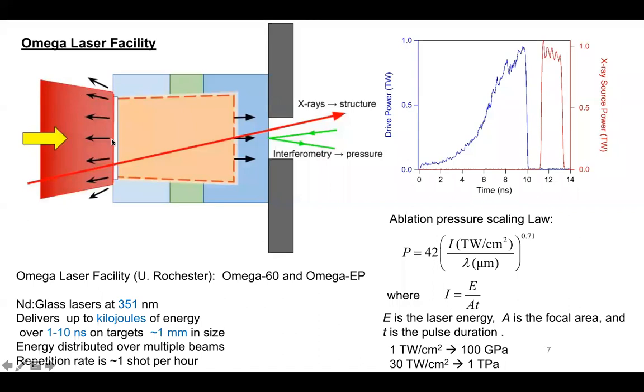We drive off a plasma at high velocity, heating it intensively, and drive a compression wave into the sample, which reverberates between the two windows and rapidly brings the sample up to an equilibrium state. And then this is attached to a metal foil with a hole in it. That gives us access for an interferometer that we can use to measure pressure and enables us to collimate an X-ray beam that we generate in order to carry out diffraction experiments.